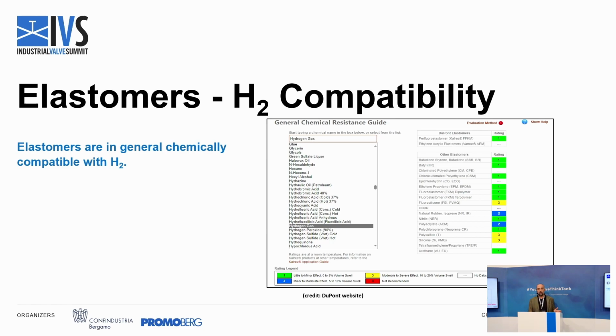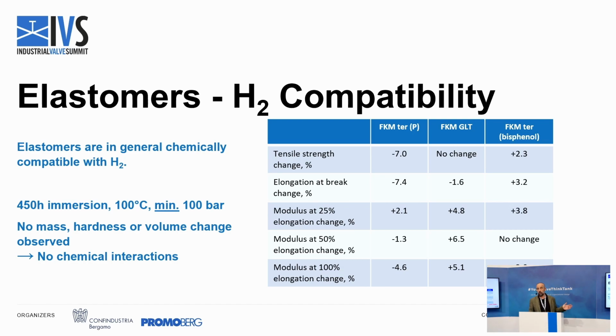As for CO2, we can say that the compatibility of most elastomers with hydrogen is basically perfect. There's no chemical interaction, except for some kinds of elastomer, but for the most used elastomers in the oil and gas industry, we have no chemical interaction whatsoever between the elastomer chains and hydrogen. There's a lot of study on this. We also ran our testing with high pressure hydrogen, 100% hydrogen, high pressure, high temperature.